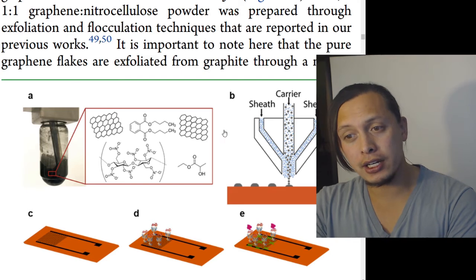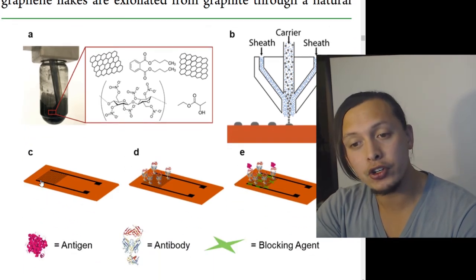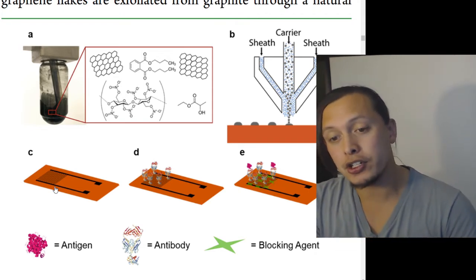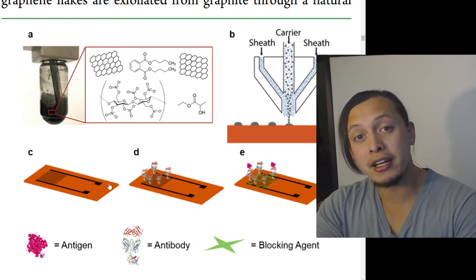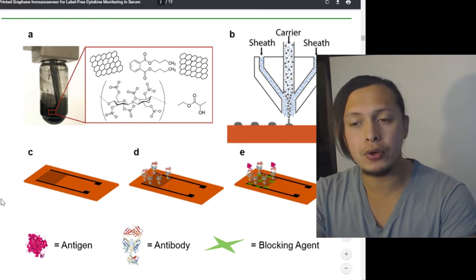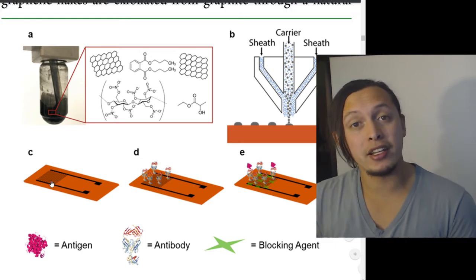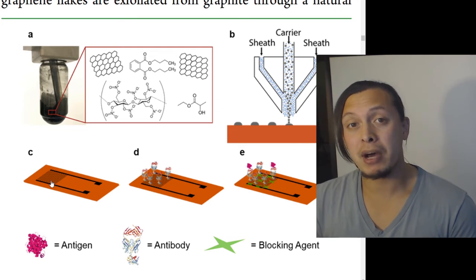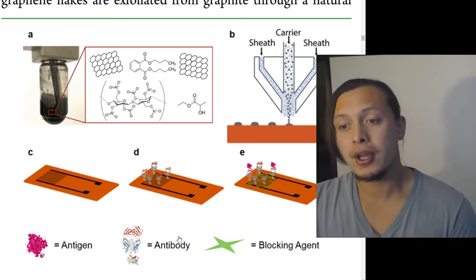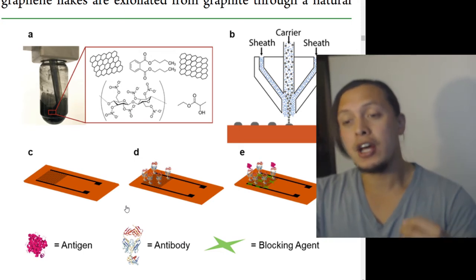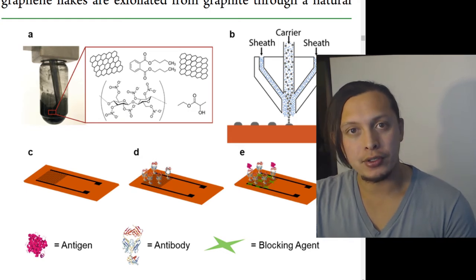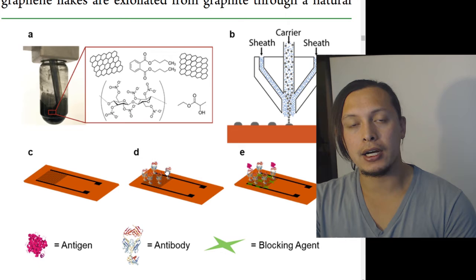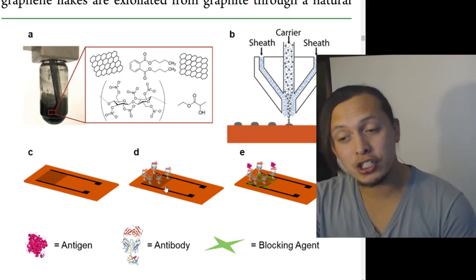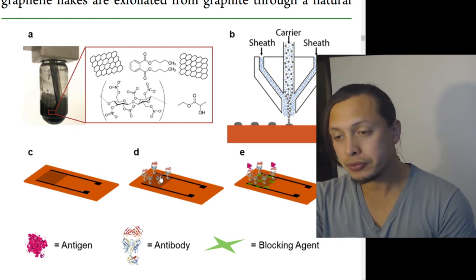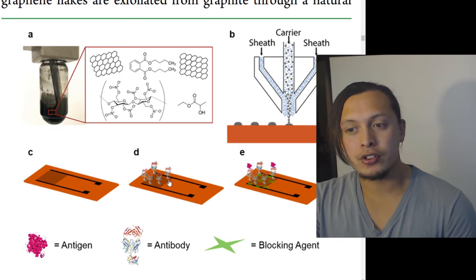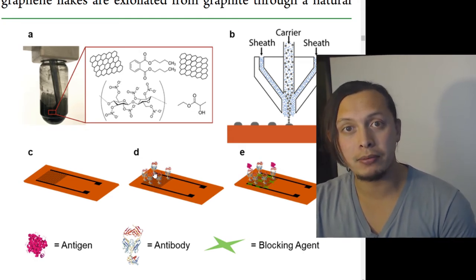But anyways, we are using this to create these interdigitated electrodes, and here you can see these digits that are intertwined with each other, and they're on two electrodes, and they're on this polyimide film, which is in orange, I believe. And what they do is they will put it into an annealing process to add some different chemical modifications to the electrodes or the digits. By adding those chemical modifications, they are then able to attach these antibodies. Here they're using an antibody for interleukin 6 and an antibody for interferon gamma. So they are able to attach these antibodies to this graphene. And then they also have to add a blocking agent to help prevent random stuff from sticking to the unbonded parts of the graphene.